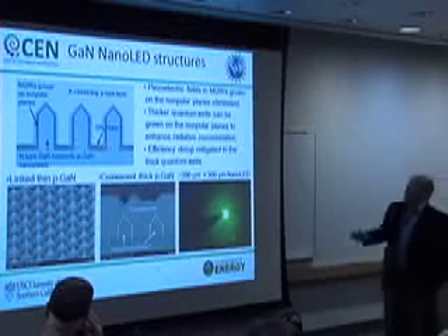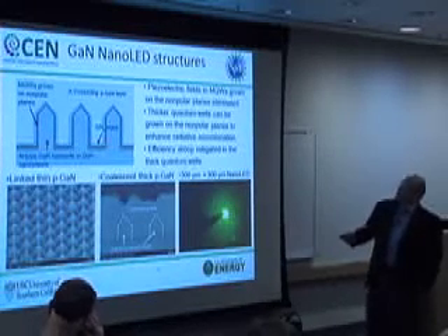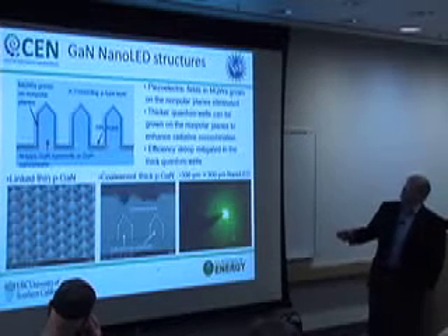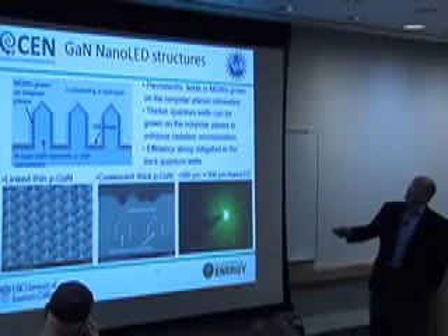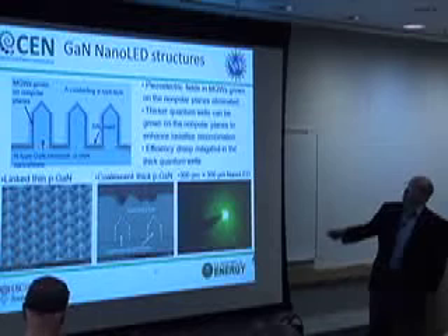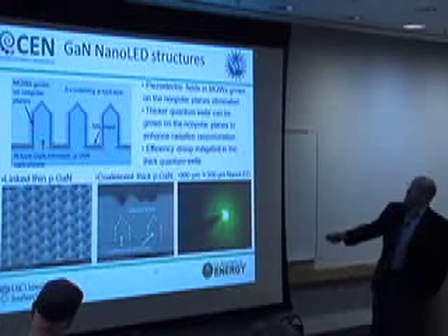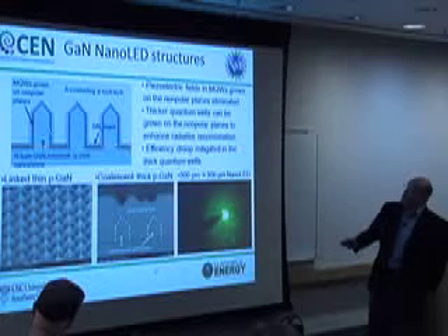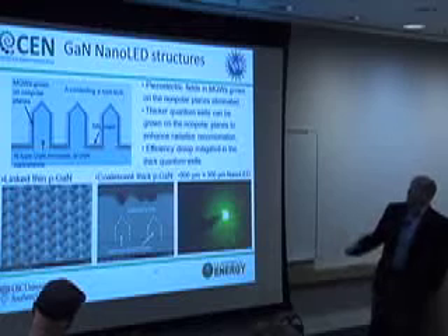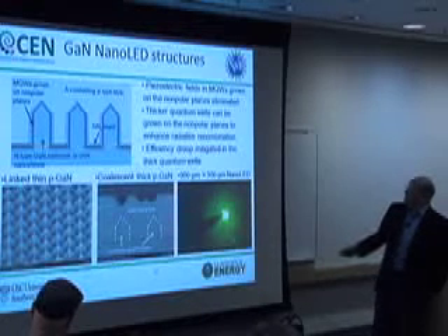Okay. So how do you turn these into LEDs? Well, one way to do that is to take the nanorods with the quantum wells and then grow a P layer that coalesces the layers so that we have a P layer that contacts the outer perimeter of all of these nanorods. We do that while embedding the mask region here by changing the growth conditions. And we've made LEDs out of that structure.